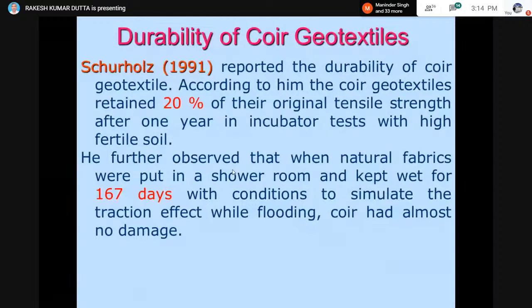And the entire thing was put in an incubator at a fixed temperature and humidity. Then after 1 year, he tested the strength and he found that the coir geotextile was able to retain 20% of its original strength. That was the initial study which was reported long back in the year 1991.